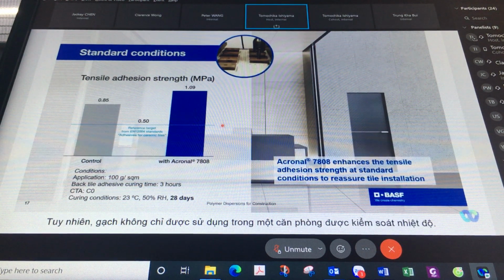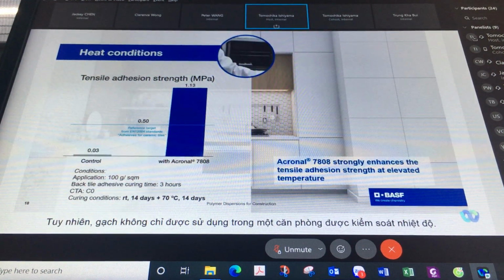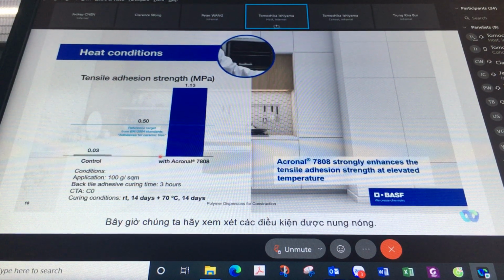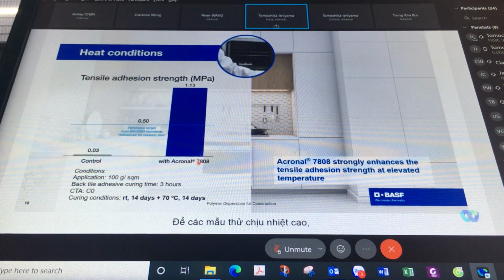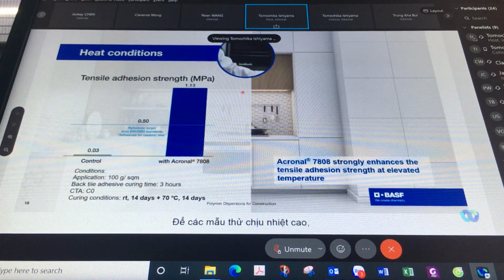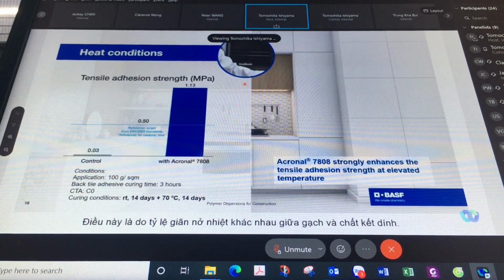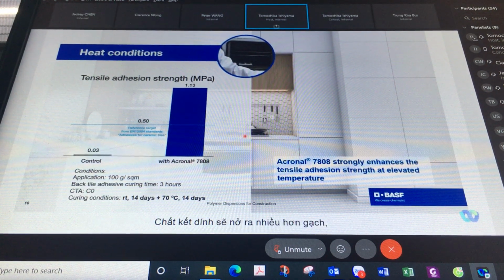However, tiles are not only applied in a temperature-controlled room. Let's now look into heated conditions. Once the specimens are subjected to high heat, the adhesion performance drops dramatically. This is because of the different thermal expansion rate between tile and adhesive. The adhesive will try to expand more than the tile, resulting in high shear stress at the bonding surface.